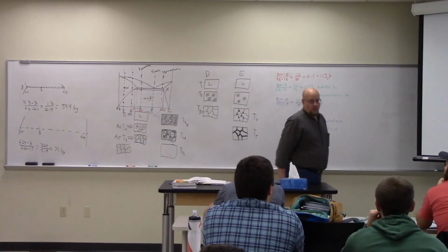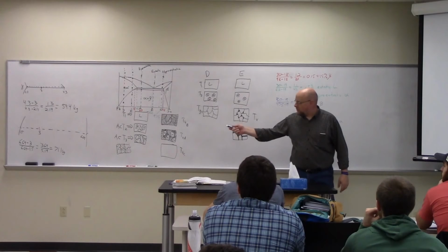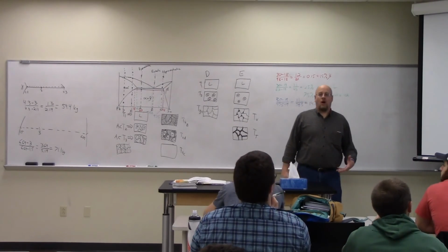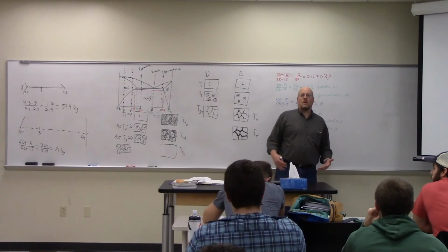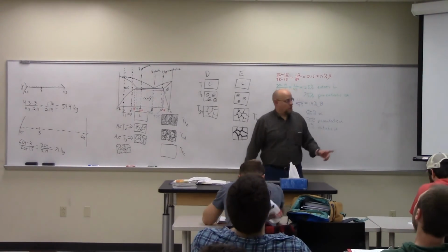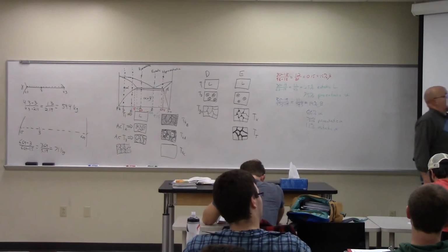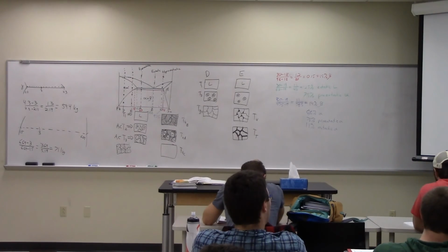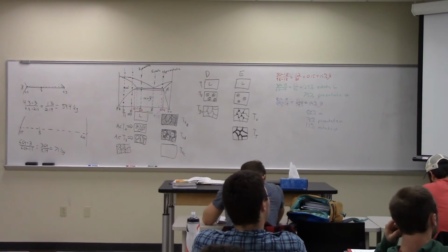No, the rest, oh, you mean the other 28.9 kilograms is then cementite. And all the cementite would be in a eutectic composition, a eutectic microstructure. When I drop down here at 3%, the only place cementite ever forms is in the eutectic. So 100% of the cementite is going to be in the eutectic.